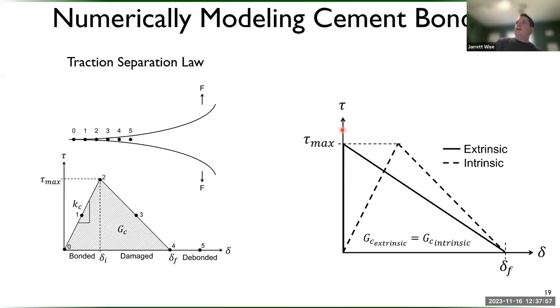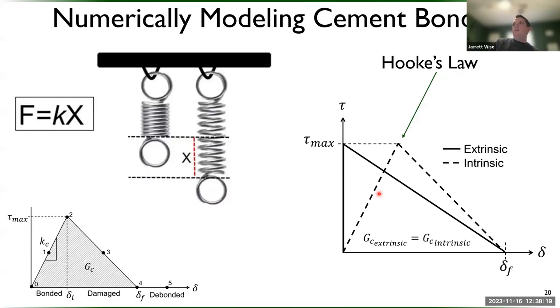The aspect that we are really curious about is there's two ways to look at this. Either you're going to get an extrinsic model where you're saying that the bond is staying bonded until you hit that max stress and then it's breaking, or an intrinsic model where there's some sort of linear elastic effect on the cement bond. And the real way to think of that is basically, does the cement act as a spring? Does it follow Hooke's law, where you can start to pull the cement and the steel further apart and it goes back how it was, unless you hit this critical separation distance?